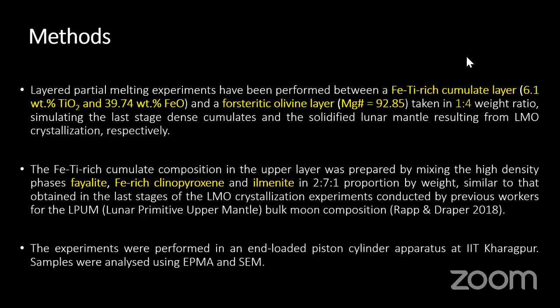On top of that, we have given an iron-titanium-rich cumulate layer, which, as given in this slide, has about 6.1 weight% titanium oxide and 39.74% FeO, iron oxide. We prepared this composition by mixing the high density phases like fayalite, which is iron-rich olivine, iron-rich clinopyroxene, and ilmenite in a 2:7:1 proportion by weight, which was similar to that obtained in the LMO crystallization experiments conducted by Rapp and Draper 2018.